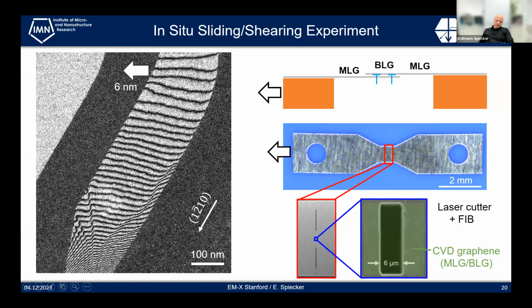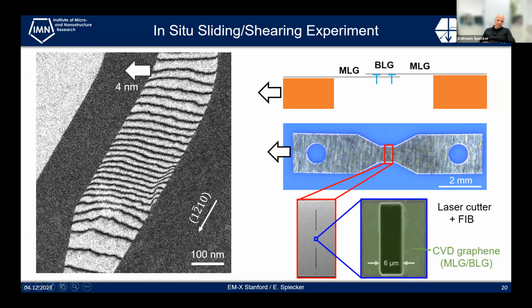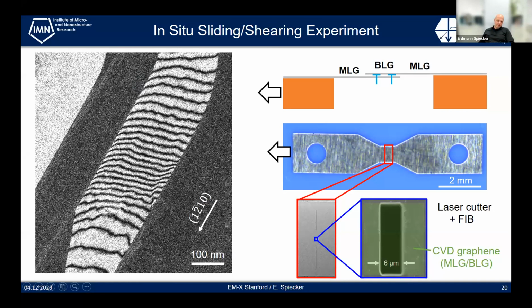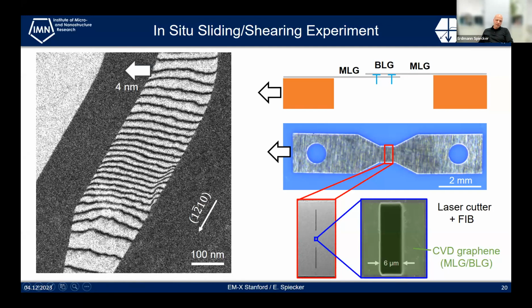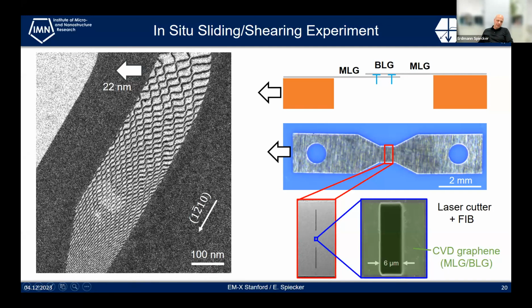I want to say a few things. First of all, you cannot see all the dislocations at the same time, because in one of the dark field images you see only two or three types of these dislocations. There's a third dislocation type which you cannot see, so you need more than one dark field image. Therefore the network here, for example, looks a little bit asymmetric. There's another dislocation line family which is not visible here.